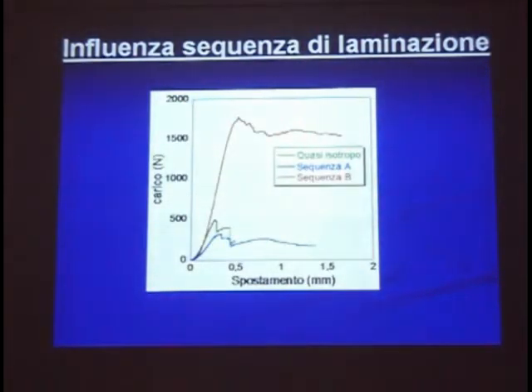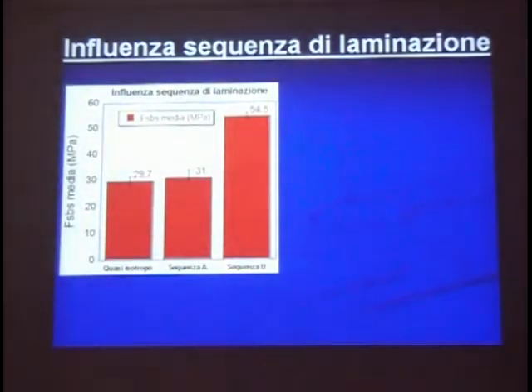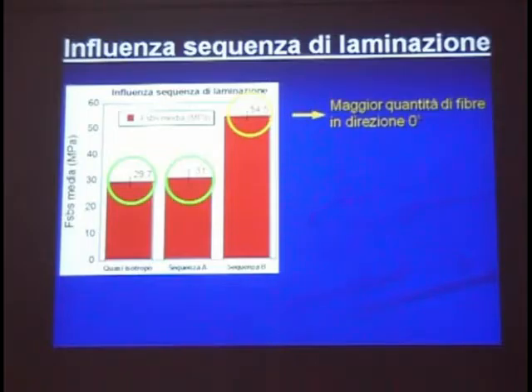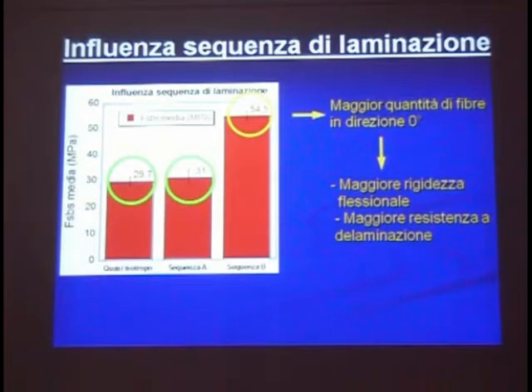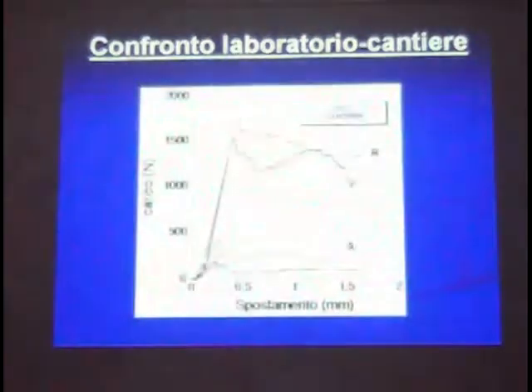You will see the sequence B, which has a lot of layers in the 0 degree, is quite stronger than the other 2 quasi-isotropic sequences, so much higher load and fracture energy, and this results in a much higher delamination strength, first delamination strength for the sequence B. So the conclusion is that if you have more fibers in the 0 direction, of course your sample is more rigid, and then you get higher delamination resistance.